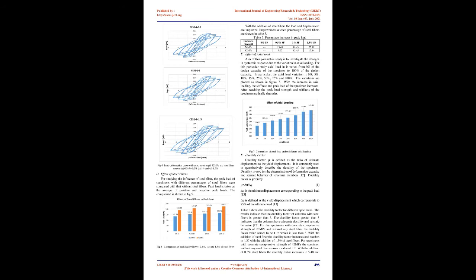Fig. 3 shows the load deformation curve for specimens with concrete compressive strength of 26 MPa and percentage of steel fiber varying from 0% to 1.5%. Fig. 4 shows the load deformation curve with concrete compressive strength of 42 MPa and varying the steel fiber content. With the increase in number of cycles, the lateral load also increases and reaches a peak value. With further increase in the cycles, the load decreases and the lateral deformation continues to increase. With the addition of steel fiber, the specimen shows an increase in lateral load and deformation.